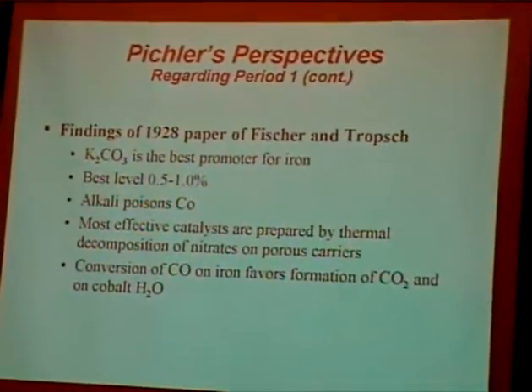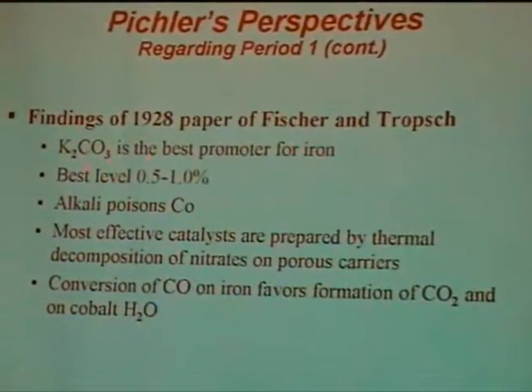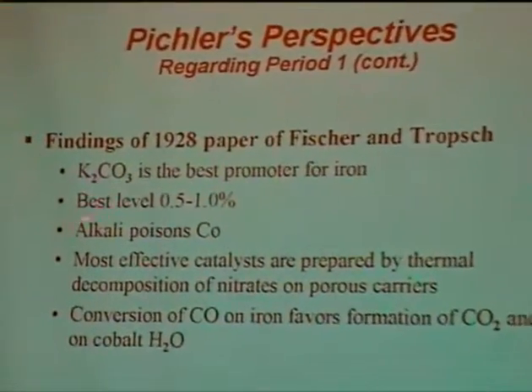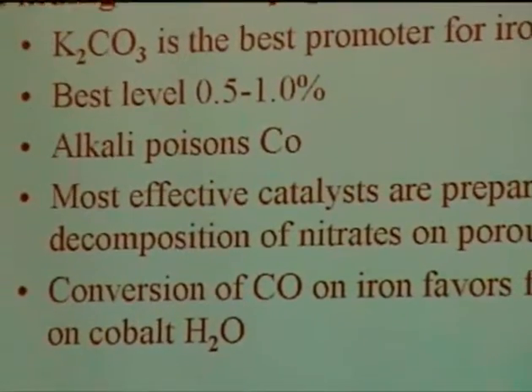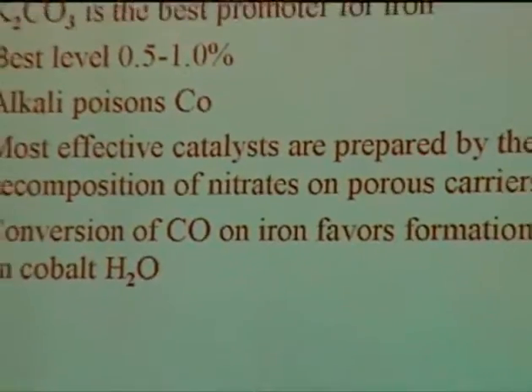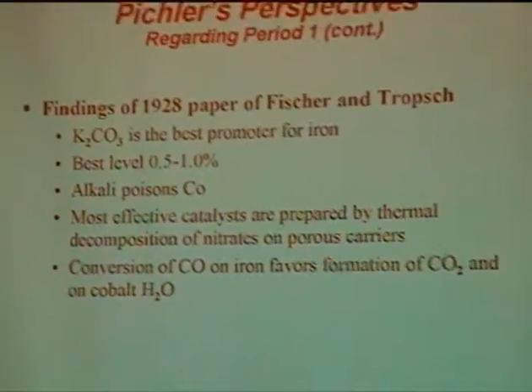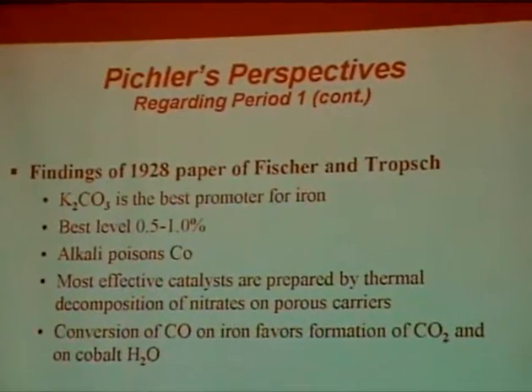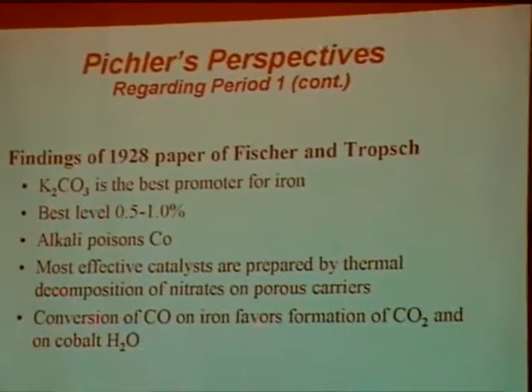In their 1928 paper, Fischer and Tropsch provide additional insights. Potassium carbonate is the best promoter for iron, with the best level around 0.5 to 1%. But alkali poisons cobalt catalysts, and the most effective catalysts are prepared by thermal decomposition of nitrates on porous carriers. This is a statement I've seen in a lot of recent patents.